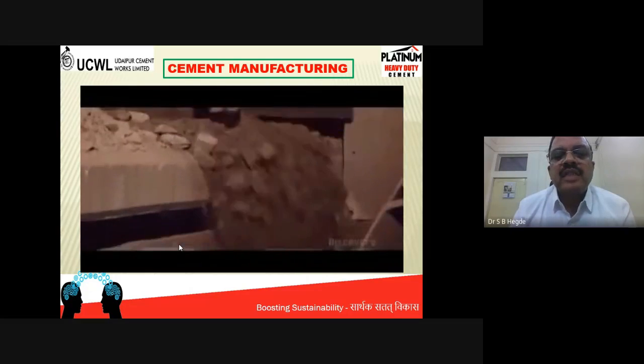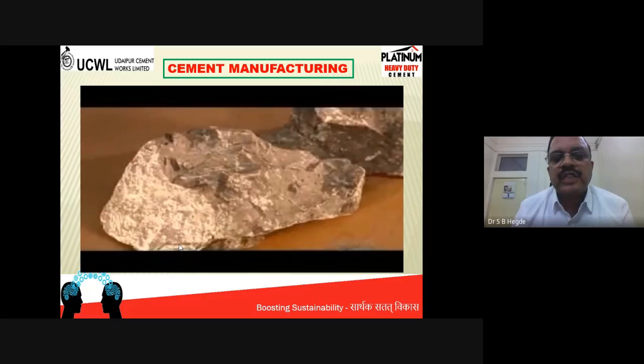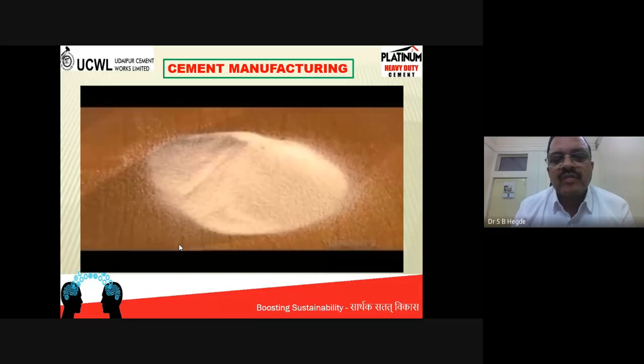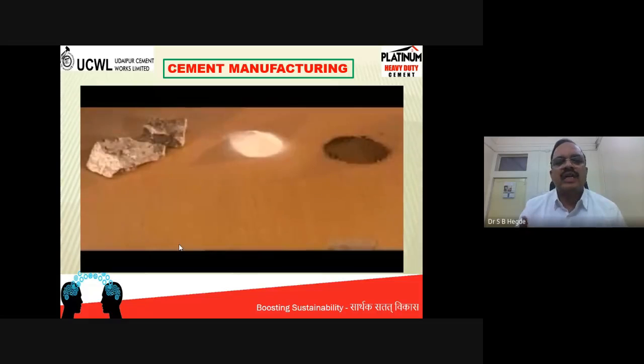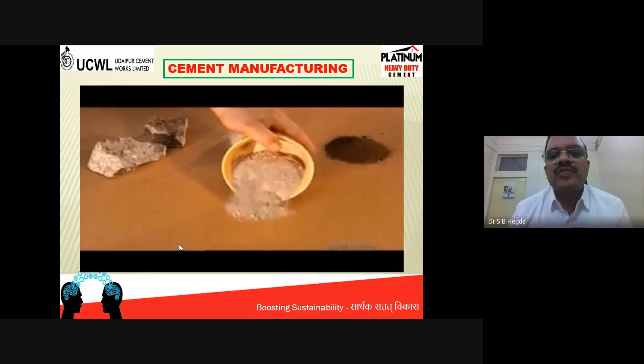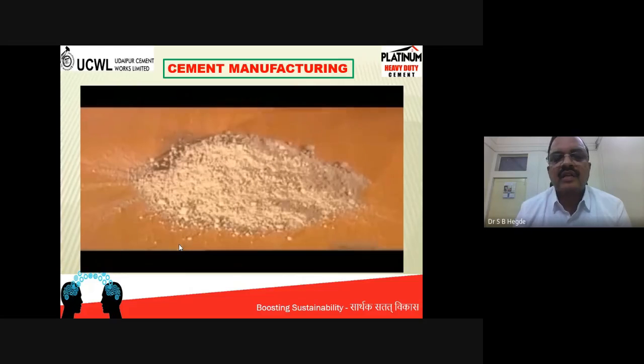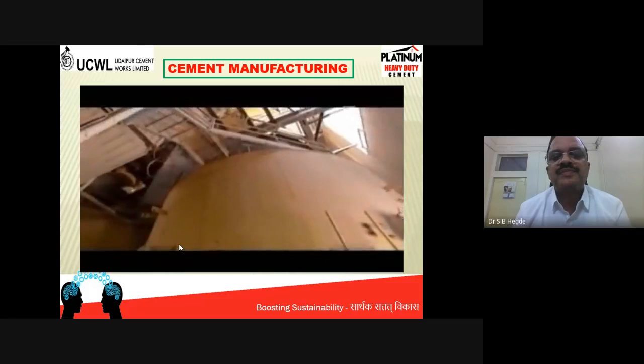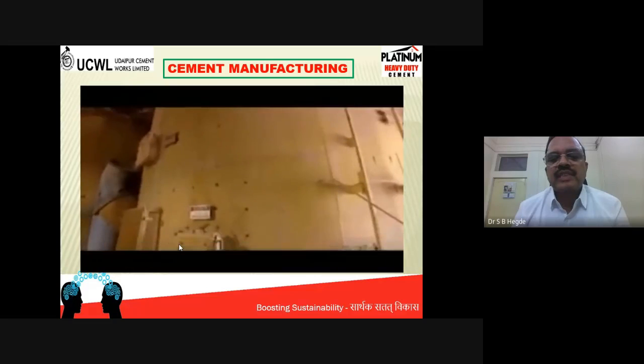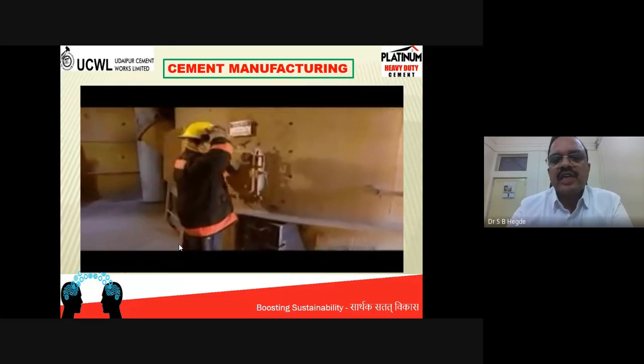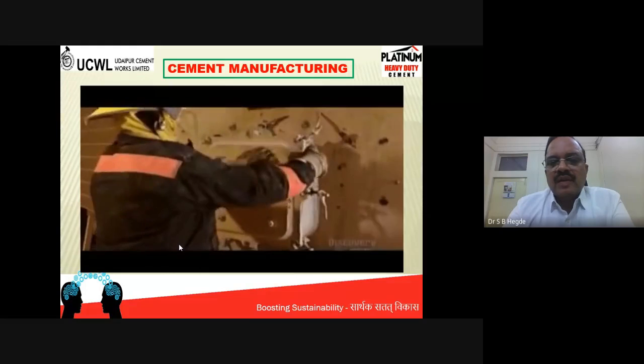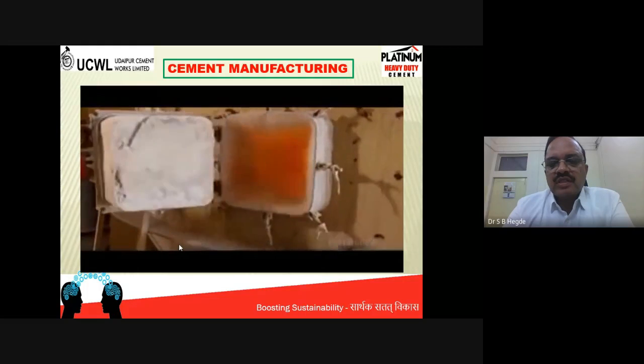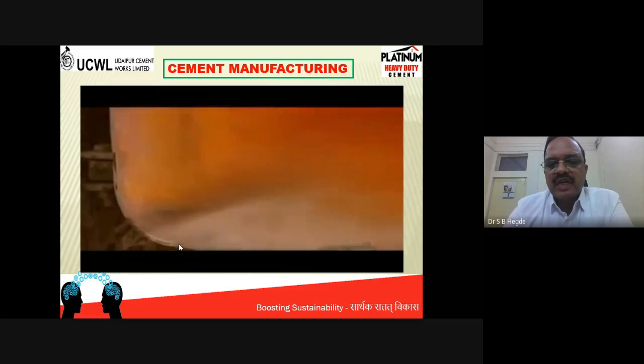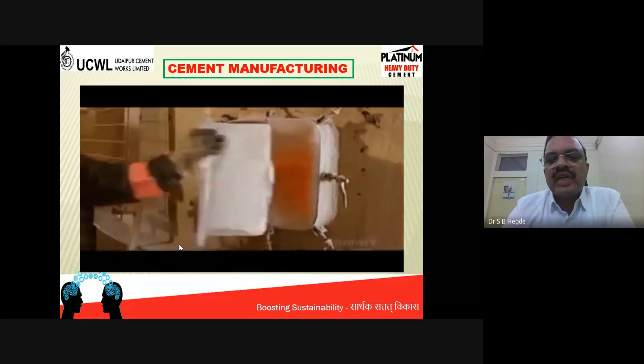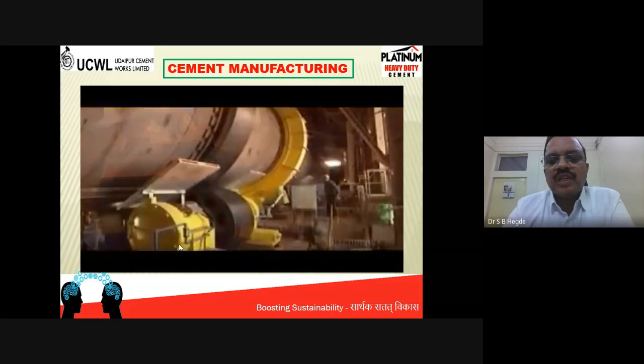This has been filled in a stockpile, and you can see the limestone transported inside the raw mill, where different ingredients, silica carriers, alumina and iron carriers, will be dosed and ground in a mill called the raw mill. Once ground, the powder is stored in a silo. You can see the silo now. For quality assurance, this will be analyzed on an hourly basis, and this material will be injected into a kiln where it is fired at 1450 degrees centigrade.